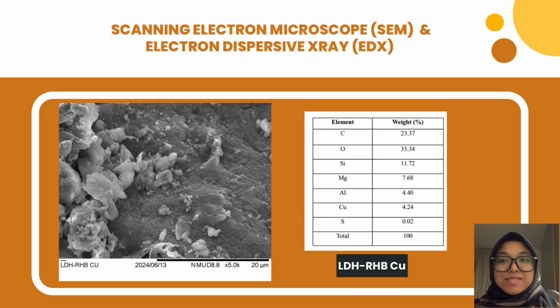Now, let us review the SEM EDX results after the composite absorbed copper ions in copper SW samples. The SEM image displayed a more granular and less porous surface morphology with visible aggregation of fine particles. EDX analysis confirmed the presence of copper, with the following elemental compositions: carbon, oxygen, silicon, magnesium, aluminium, and also the percentage of copper is 4.24%. These changes suggest successful absorption of copper ions with the formation of aggregation, which indicates the effective incorporation within the composite.